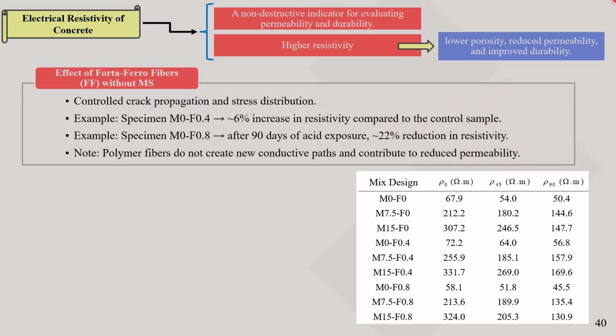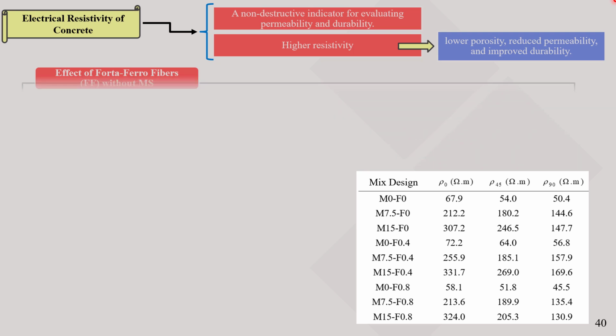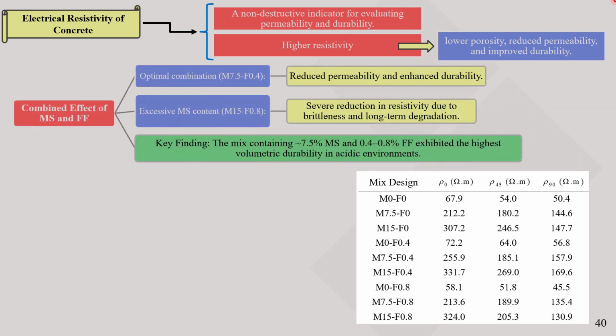When analyzing the effect of fibers without microsilica, the fibers had little impact on volumetric electrical resistivity, and at higher percentages, the resistivity even decreased compared to the reference sample. Nevertheless, over the 90-day period, the relative resistivity was better maintained because the fibers blocked penetration paths and prevented acid from entering the concrete. The combined effect of microsilica and fibers showed that using an optimal ratio, 0.4% fibers and 7.5% microsilica, reduces permeability and increases resistivity.